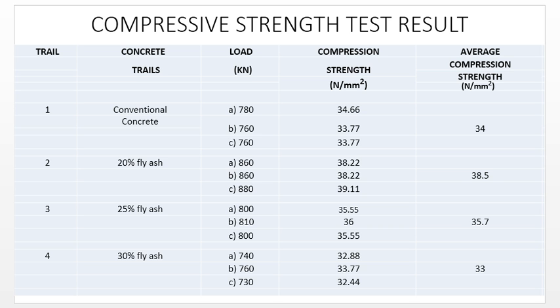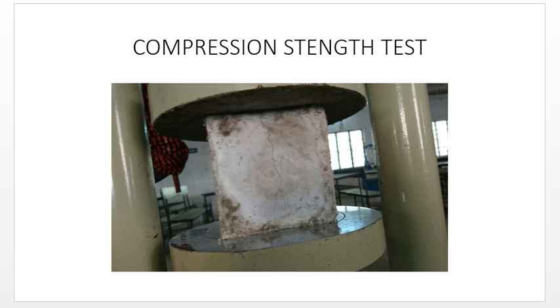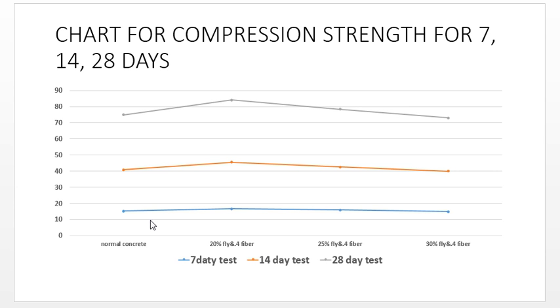While replacing cement by 20%, it will give the maximum compression strength, that is 38.5 Newton per mm square. Beyond that 20%, the strength is going to decrease. The graph shows that 20% fly ash replacement gives the maximum compression strength.